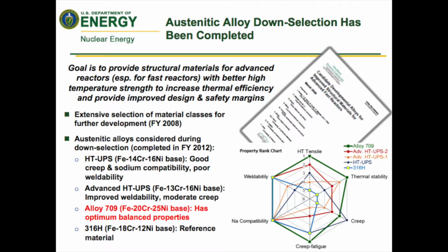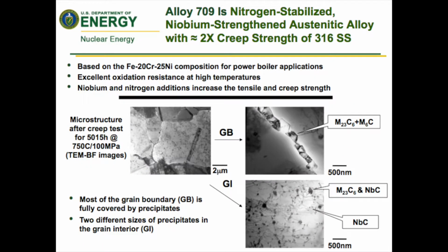So what we've ended up doing is a down select of this material about 2 years ago from the other candidates because it showed on the whole the full palette of improved properties, but specifically it showed a substantial improvement in strength.